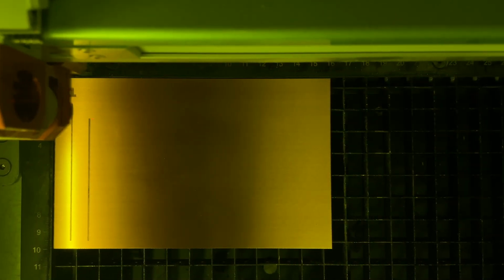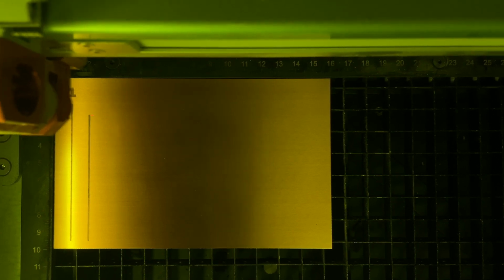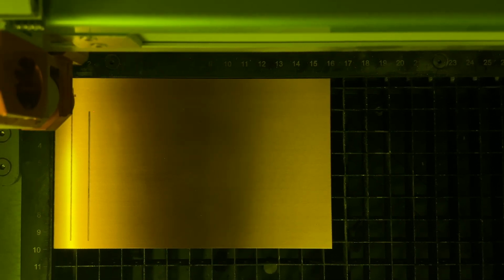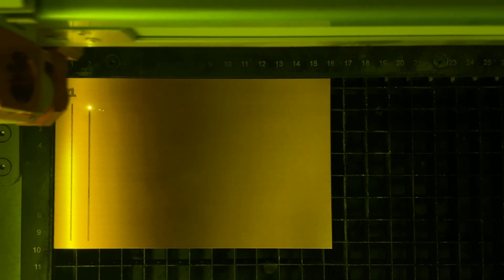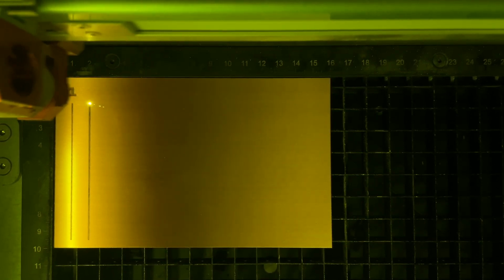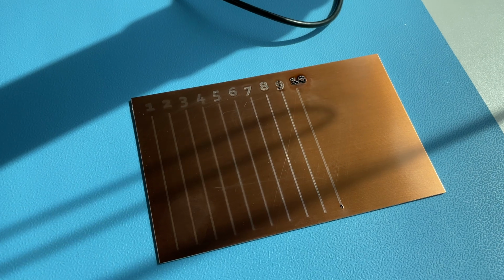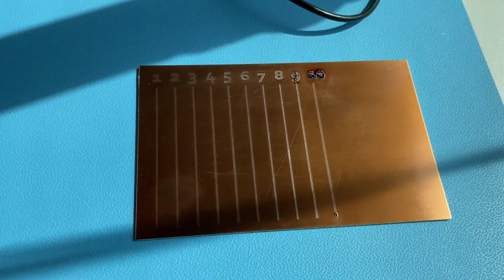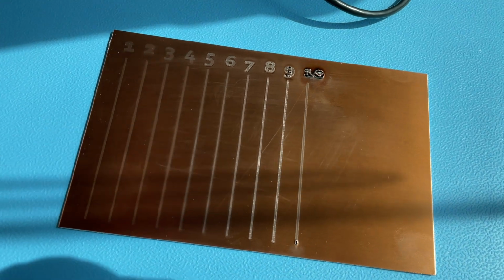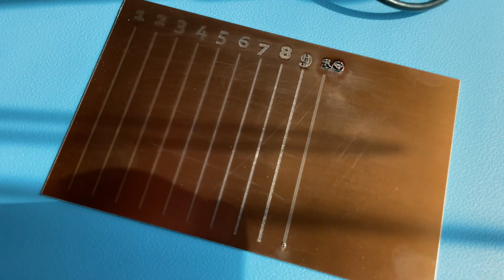What we are attempting is to laser the layer directly onto the photosensitive coating, but to do so you would need a UV laser, which we unfortunately did not have available. So we used a normal CO2 laser and basically tried to burn the whole photosensitive coating completely away. We had different tests, 1 to 10 different settings of the laser, starting with 40% power and 10% speed until the 5th test layer, and afterwards decreasing the speed until 0.5% instead of 10%.